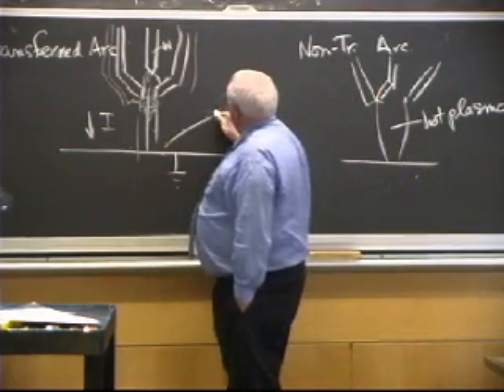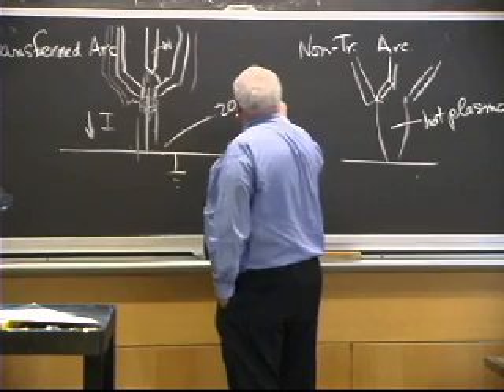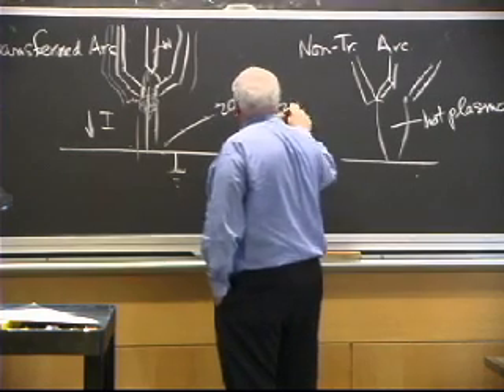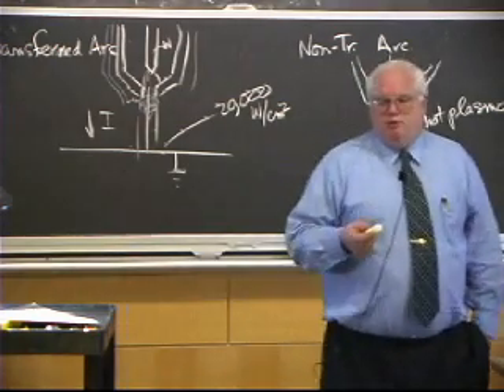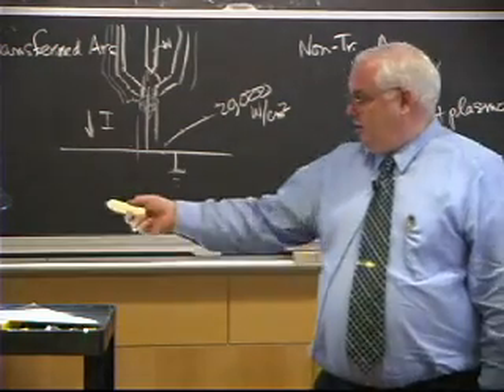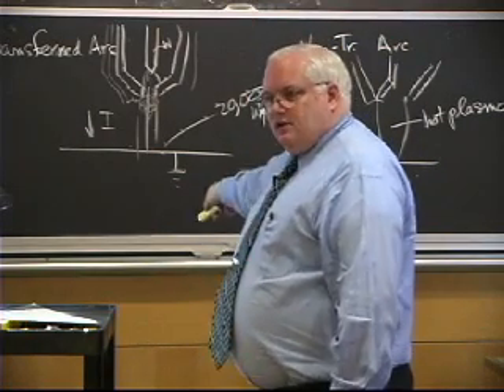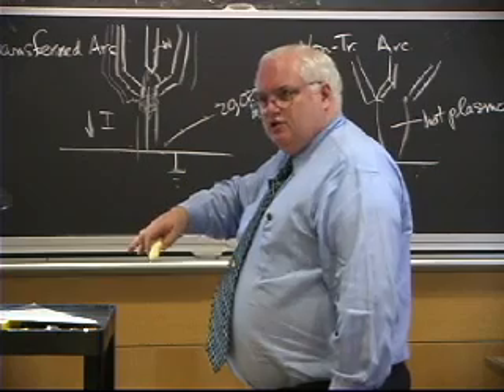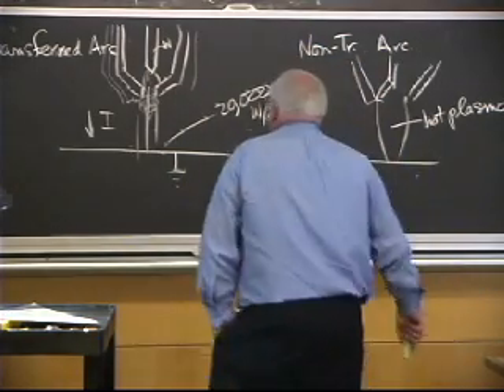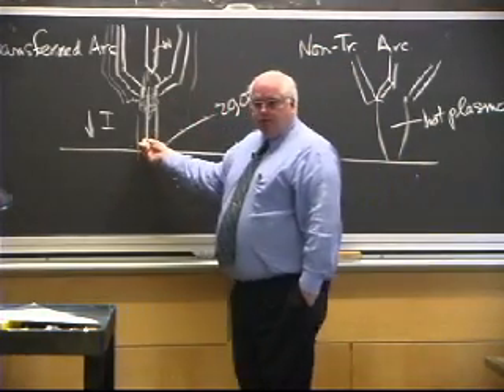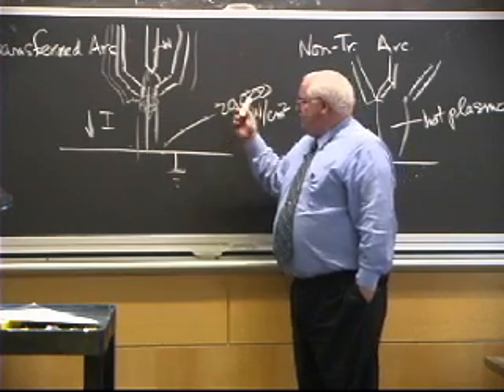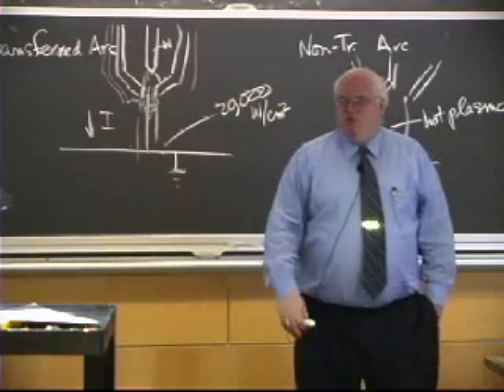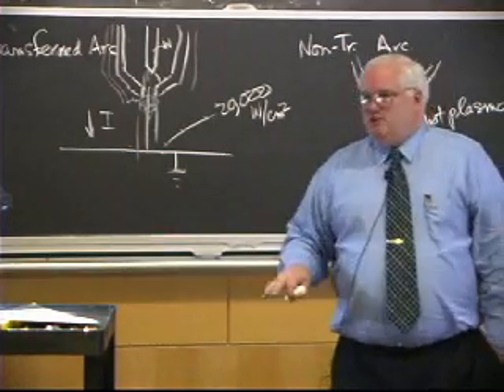But the difference is, here I can get up to 20,000 watts per square centimeter, about double what I can get out of a simple gas tungsten arc, which is about 10,000 watts per square centimeter. Why? Because I've got a higher velocity, my boundary layer is thinner, I get more conduction across the boundary layer. There's no more heat carried by the electrons, it's still the same 80 or 90%, but instead of only 10 or 20% carried across a thicker boundary layer, I can get substantially more heat because of a much higher velocity coming out of there.